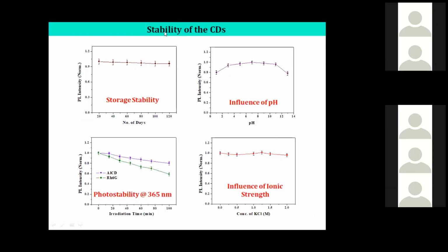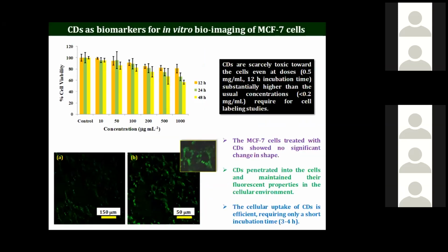When you want to apply this material for bioimaging, you look at storage stability, wide range of pH application, and photo stability. These are all important—it's fairly stable. Also, the influence of ionic strength on fluorescence intensity matters, since there's a possibility of fluorescence quenching at higher ionic strength depending on the material. These are the parameters we analyze to find out whether it can be used for the bioimaging application.